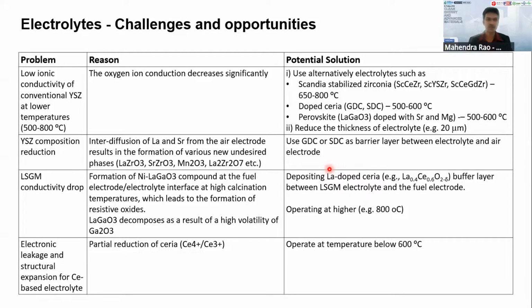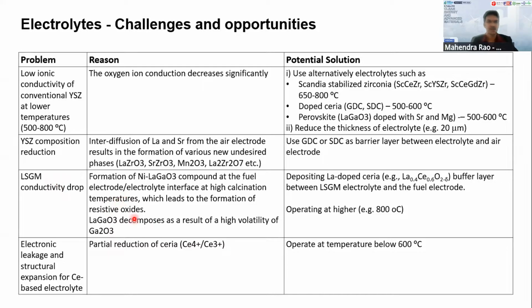And then we know lanthanum gallate is a very good material, but it has some chemical stability issues due to phase separation. Some of the opportunity is to reduce the thickness, to reduce the polarization resistance of the existing material. So this is some of the way of improving the conduction of the electrolyte.